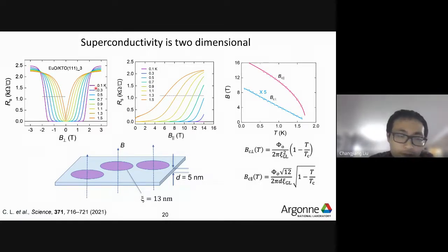So let me continue. We further did some magnetic transport measurements on this interfacial superconductor. So we did the out-of-plane magnetic transport. Basically, here we can measure the critical field as a function of temperature. So this is the in-plane, out-of-plane. Now, when we apply a magnetic field in the same plane, we found that the superconducting transition is robust against the in-plane magnetic field, meaning the critical field is significantly higher. You see that at 0.1 Kelvin, even at a 14 Tesla field, there's no sign of suppression of superconductivity. While for out-of-plane, at 0.1 K, the critical field is around 1.7 Tesla.